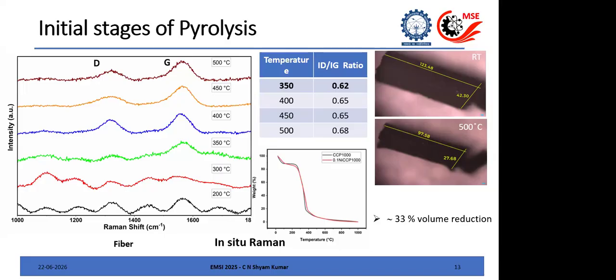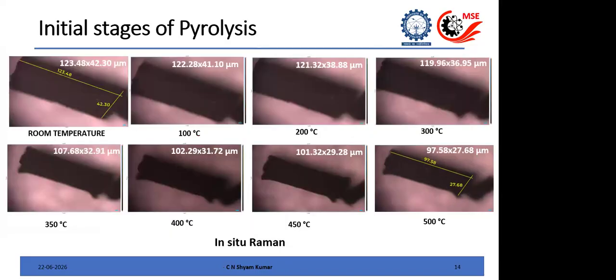lignocellulose materials also. You can also look at the shrinkage, because when the volatiles are removed, there will be a change in the size of the sample. You can see the maximum change is happening somewhere between 300 and 400 degrees Celsius, coming down from 120 micrometers to 100 micrometers. So you can correlate this. All these insights will help you to tune it better.